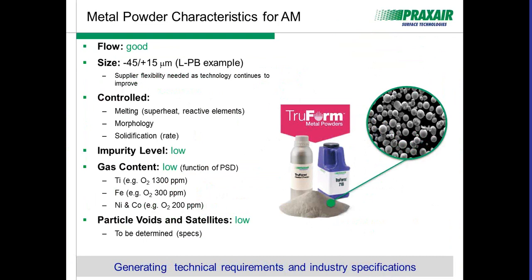When we look at the flowability of powder, we always want to think about particle-to-particle friction. As the particle shape changes from spherical to irregular or faceted, you create more point contacts that can create an increased amount of friction, which prevents the powders from sliding past each other. That can disrupt the flow. So our customers want us to work together with them to understand how we change the atomization characteristics and the physics of our atomization process to create more of a spherical morphology and eliminate surface defects.